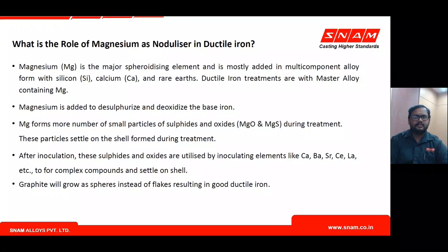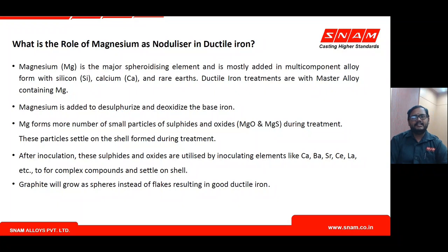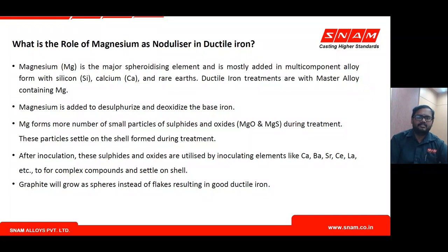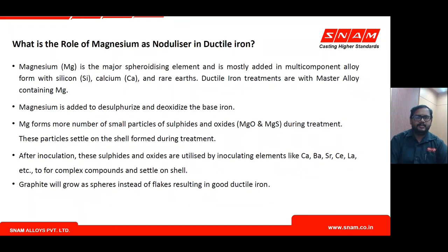In addition to the compounds formed by magnesium, inoculating elements such as calcium, barium, strontium, cerium, and lanthanum are added separately. These form complex compounds along with magnesium and silicates, creating a substrate shell. With all these compounds and formations, graphite precipitates and grows into spheres, producing good ductile iron with good nodularity instead of flake graphite.